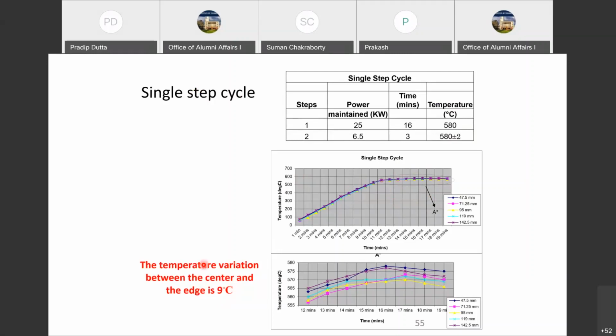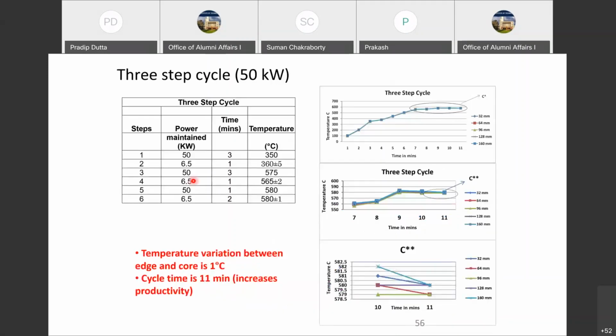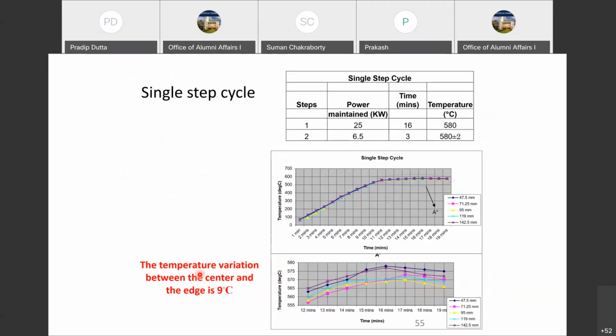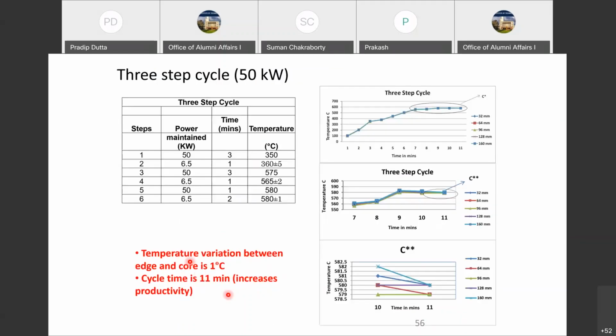So what we did was modeling, and according to the model, we altered the experiment and converted it into a 3-step cycle: heating, soaking, and then heating. And it all took place in a very short time, only 11 minutes, as against last time, I don't know how much it took, but much more than that, I think nearly double the time. Within about 11 minutes, we could achieve a uniform temperature between edge and core, within about 1 degree Celsius. So this is how we get the temperature distribution across the billet.